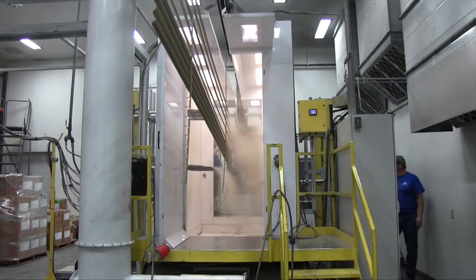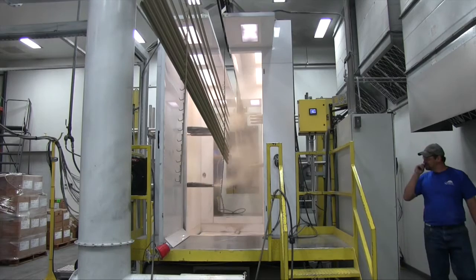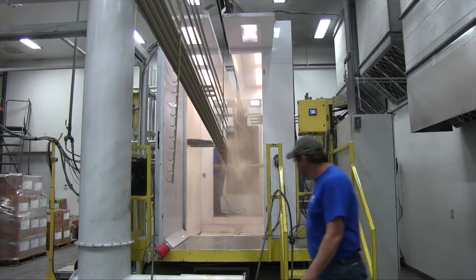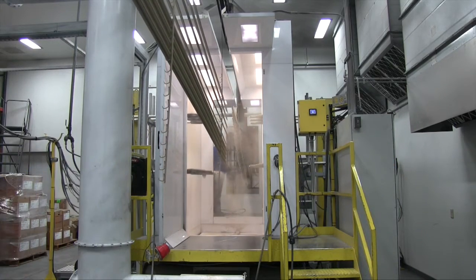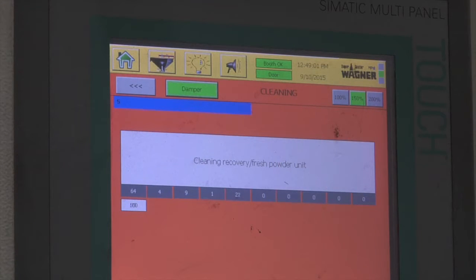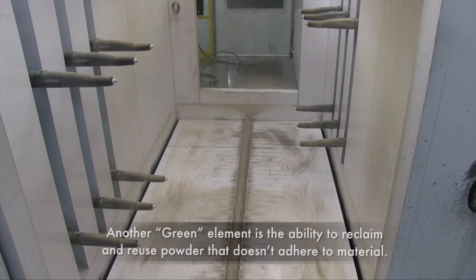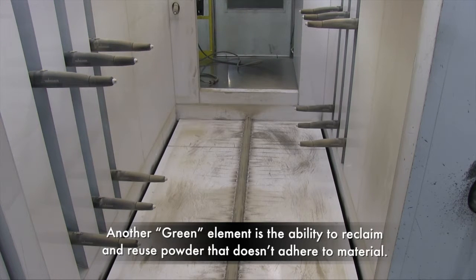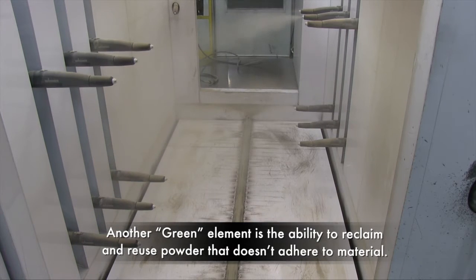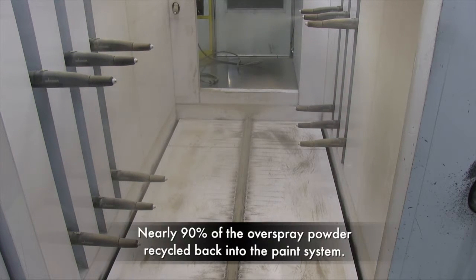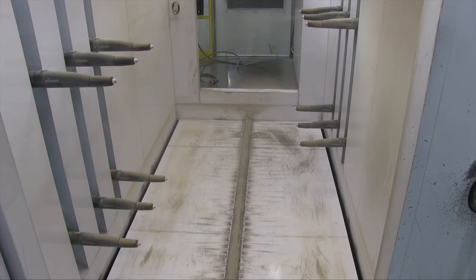The complete paint center utilizes an advanced air makeup system that equalizes the air pressure throughout the cleaning, painting, and curing process, which prevents dust and debris from getting caught up in the air and onto the aluminum traveling through the paint process. Another green element is the ability to reclaim and reuse powder that doesn't adhere to the material. It's collected at the bottom of the booth and then sent to a reclaim bin. Quaker's lost powder is very minimal, with over 90% of the overspray powder recycled back into the paint system.